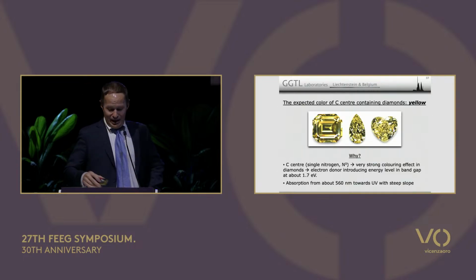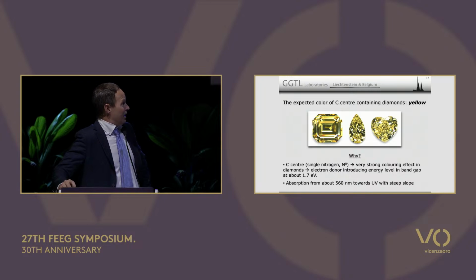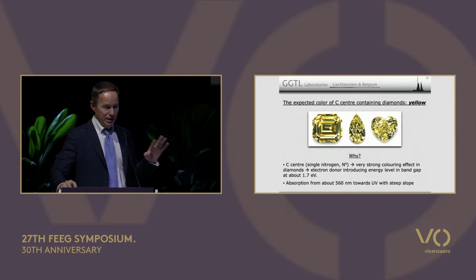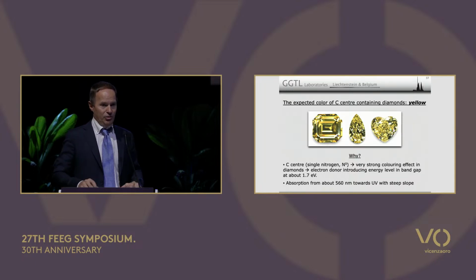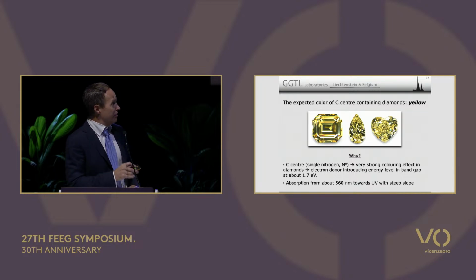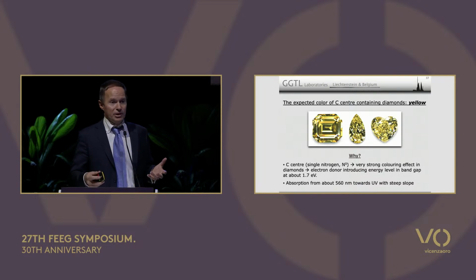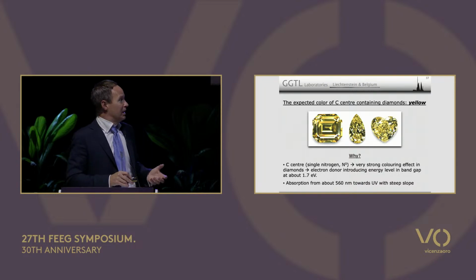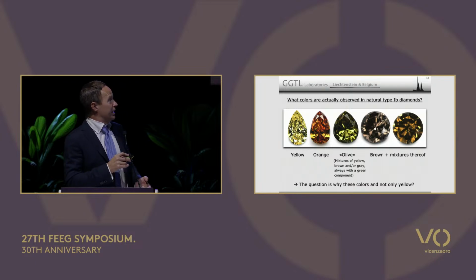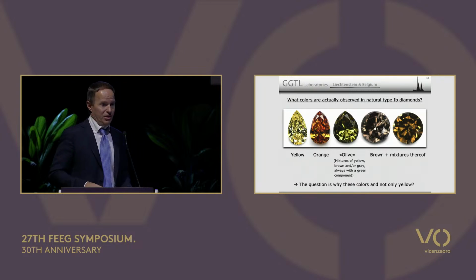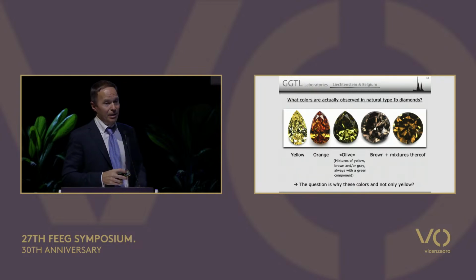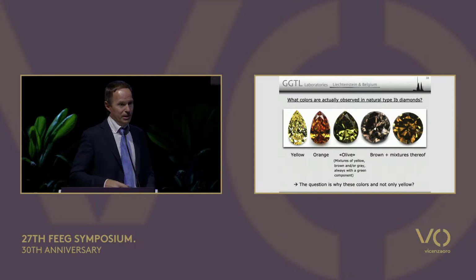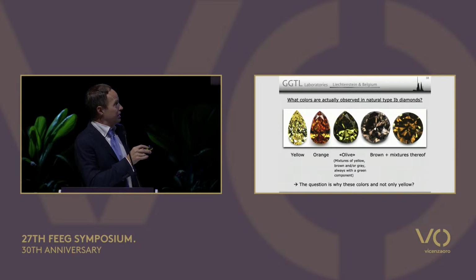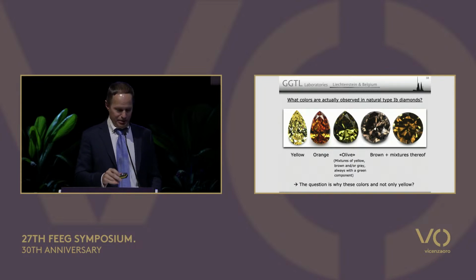Okay, so let's go a little further. Let's look at type 1b diamonds, on the same topic. Type 1b diamonds are supposed to be yellow. You have diamond with single nitrogen, and it will turn out straight yellow. The more single nitrogen you have, the more intense the color, and if you have too much, it gets a bit too dark. But they're not supposed to be this, and that's what they actually are. The vast majority of type 1b diamonds that you will see in the market are actually in this color range here. Now, why is this the case? Why are they not just yellow?